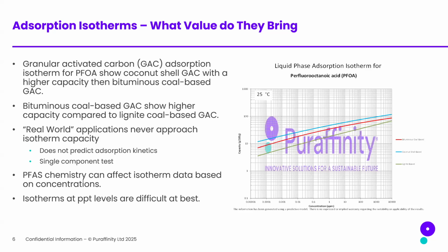If anybody's looked into detail into PFAS chemistry, it's pretty intense in terms of how PFAS compounds react. I mentioned before my master's degree is in colloids, polymers, and surfaces. One of the first classes I had was talking about forming micelles, and I said to myself, I'm never going to use that again. Well, PFAS compounds at high enough concentration form basically little balls, which are micelles. If you get to a high enough concentration, you can see an increase in adsorption capacity on various materials just because of the chemistry of the PFAS compound.